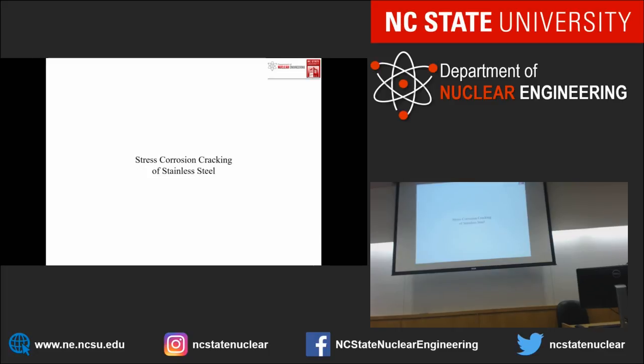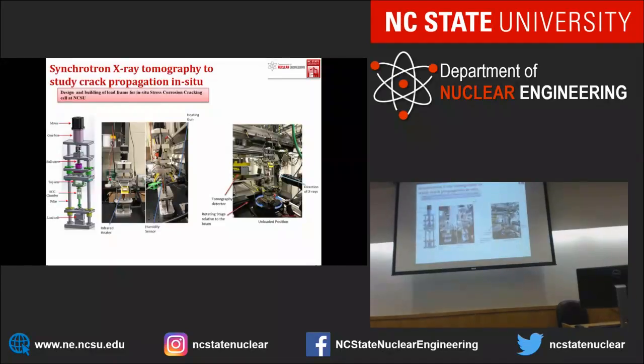And the last area we study is the stress corrosion cracking of stainless steel. Here at NC State, we designed and built a tensile machine with a stress corrosion chamber. The sample is put in a humidity environment, and the machine allows us to control the temperature, the humidity, and the load.